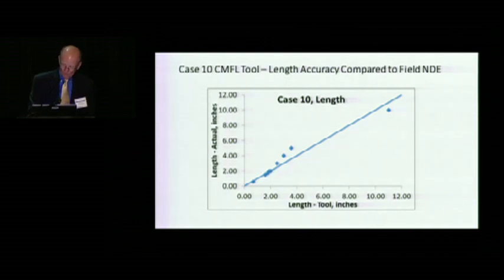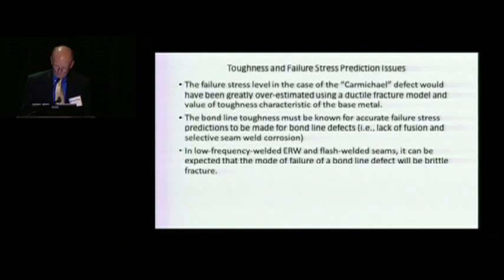Okay, here's one where the magnetic flux leakage tool did pretty well as far as the length that was measured by the actual field measurements. But what are the other issues that are really important here that we discovered? And that is that the failure stress level in the case of the Carmichael defect would have been greatly overestimated by any ductile fracture model. That's because this defect, the failure jumped into the bond line and it was brittle. So basically, you've got to deal with that with some sort of a model for brittle failure. And in low frequency pipe and flash welded pipe, that's what you can expect. That's the reality. The bond line will be brittle because of the nature of those processes.